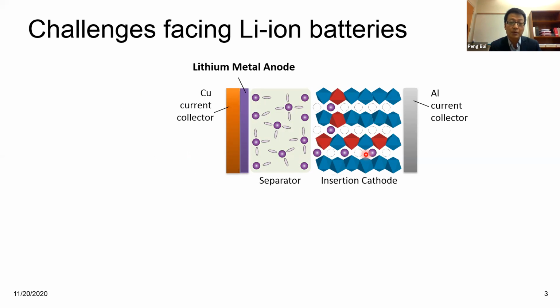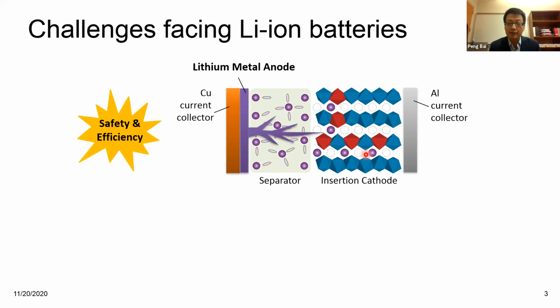But the problem is that when you do this reduction of lithium ions, this plating or electrodeposition of lithium metal, you will generate this kind of finger or tree-like structure, and it's called a dendrite. And this dendrite can grow through the nanopores of the separator and give you an internal short. That's not what we want, because batteries then can catch on fire or explode.